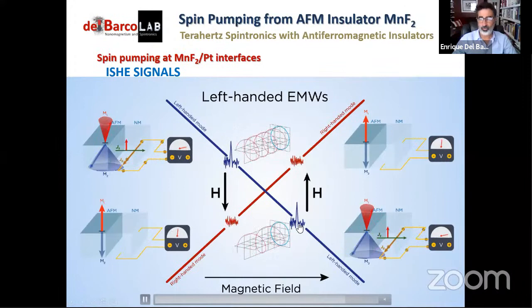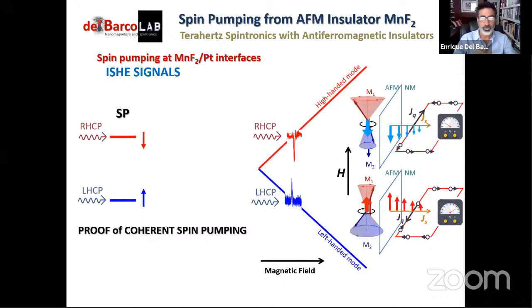This is basically what I have shown you. Well, this is the central result of this work, indeed. It's what we consider proof of coherent spin pumping at terahertz frequencies out of an antiferromagnetic material. And this is important because this is basically what you expect, right? So if we hit the system with right-handed circular polarization, we will induce dynamics or spin pumping out of the right-handed antiferromagnetic mode with the spins down and negative voltage. If we use left-handed circular polarization, the only mode that we will be able to hit is the left-handed mode that has spin going up, and it will result in a positive voltage.